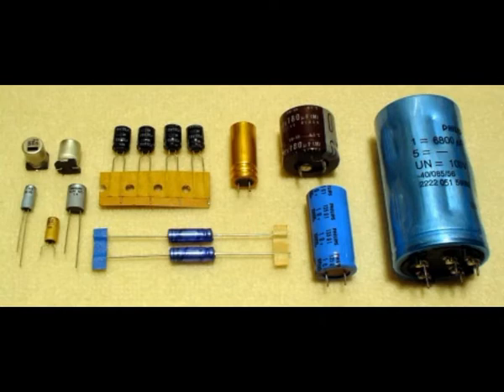During discharging, the internal construction of the capacitor reverses the internal polarity. The cathode gets an anode plus, and changes the current flow direction. Two voltages arise over these electrodes. In principle, the voltage distribution over both electrodes behaves as the reciprocal CV product of each electrode. The design rule of high cathode capacitance assures that the voltage appearing over the cathode during discharge is not higher than roughly 1.5 volts, that is its natural air-originated voltage proof. No further post-forming of the cathode foil takes place, which may lead to capacitance degradation. Then the capacitors are discharge-proof.